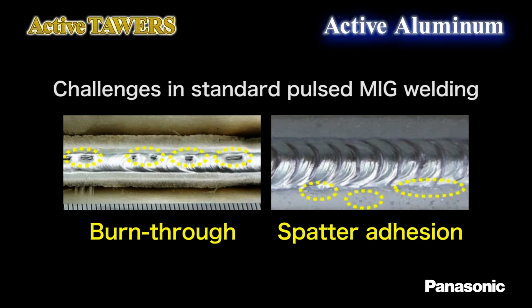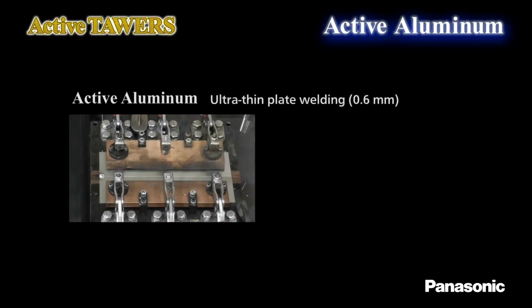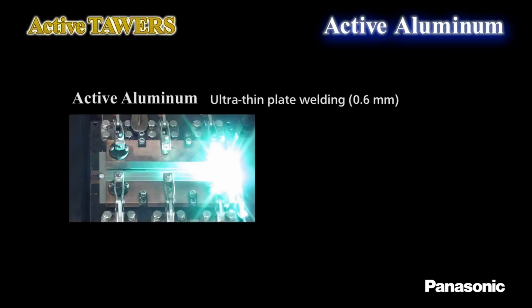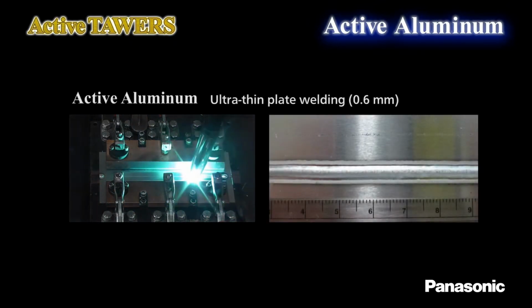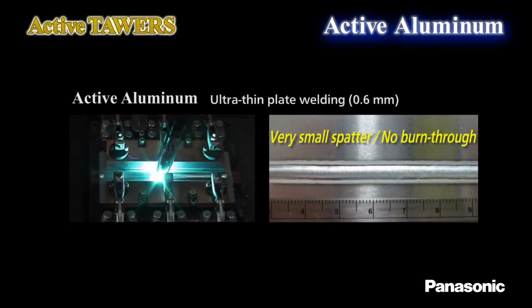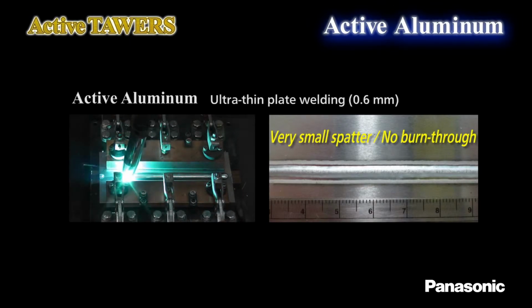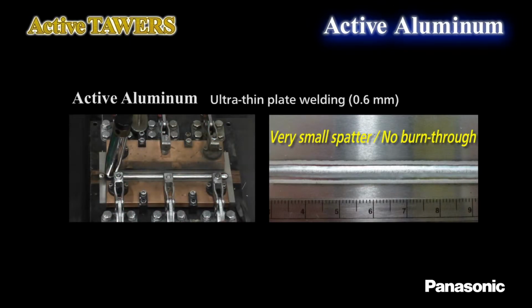However, when the wire extension changes, it causes the spatter to adhere. In the case of ultra-thin plate, heat input is high and causes burn-through. On the other hand, active aluminum smoothly opens the short circuit to enable welding with low heat input even for thin plate. That way, it is able to prevent the generation of spatter and burn-through.